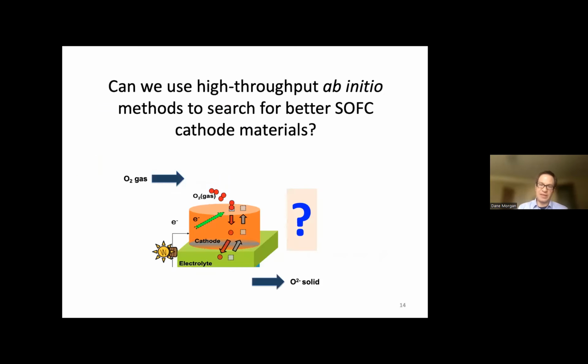I should probably say, if you go back to this picture, you might say, well, why don't you model the reaction of oxygen gas on the surface of your material and study how it splits and enters vacancies. And we actually did do work like that. We spent about 5 years studying one material, trying to understand the surfaces, surface segregation, surface defect structures, which of the many possible surfaces were active. And it just turns out to be a really complicated process. So full modeling of the full molecular scale processes is exciting and promising and interesting, but it is not high throughput. You're going to study just a handful of materials at most over a number of years if you really want to understand it that way.